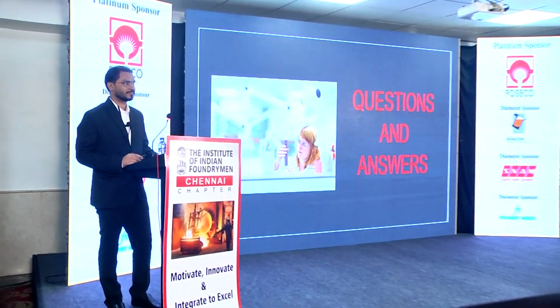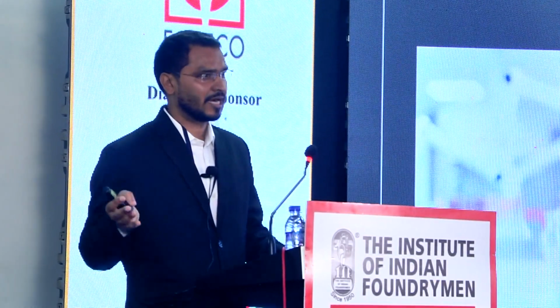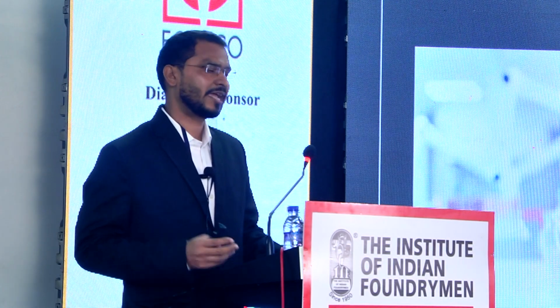Mainly automotive foundries are using water-based coatings. These coatings are available in water as well as solvent-based. Any coating, if it is available in water, can be made available with solvent. There are 4 major components in a coating: filler, carrier, binders and suspension, and other additives. The main roles are played by the filler, the binder system and the rheological conditioner. The carrier can be changed, whether it is water or alcohol.